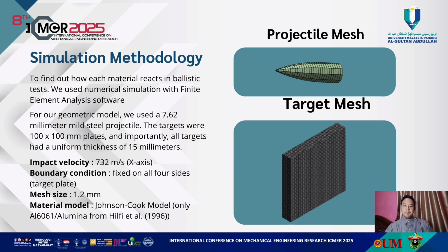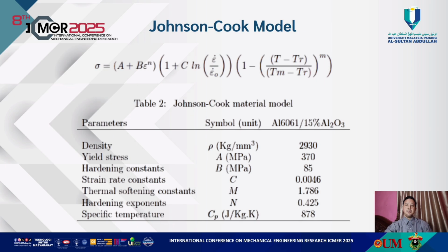The simulation was set up with an impact velocity of 732 meters per second, and all target plates were fixed on all four sides. All materials were designated as flexible, which allowed the projectile and target plate to deform upon impact. And here is the Johnson-Cook model we obtained from Hilfi and Brar. We manually added the data since the data for our composite material is not available in the software library.